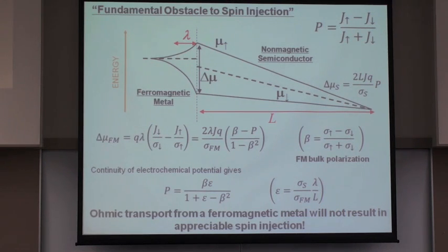And so the polarization of the current that flows in the semiconductor is very small unless the ferromagnetic bulk polarization is almost unity. Then it cancels out this one here, and the epsilon cancels out, and we can just push our 100% polarization across the interface. This has not been achieved in reality, and so what happens is that this ohmic injection, just taking a spin polarized source of ferromagnetic metal and pushing electrons across the interface by applying a voltage drop, is not going to result in spin polarized current flowing in the non-magnetic semiconductor on the other side.